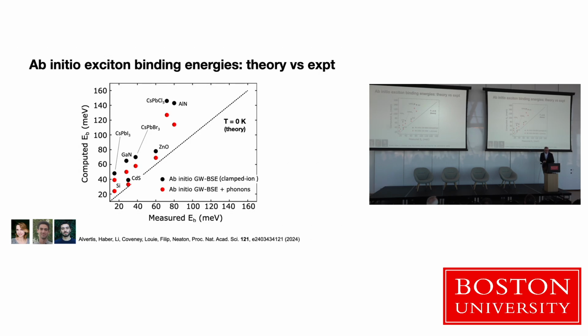And so just to give you an idea of how big of an effect these phonon effects are, even at zero temperature, there are zero-point effects. This is a zero temperature plot. On this axis, we have the computed binding energy with two different levels of theory. One is the current state of the art, and one is adding the phonons. And what you can see is that if you compare the computed binding energy and the measured binding energy, all of them are a little too high. But if you include the phonons at 0 Kelvin, then you're doing better.